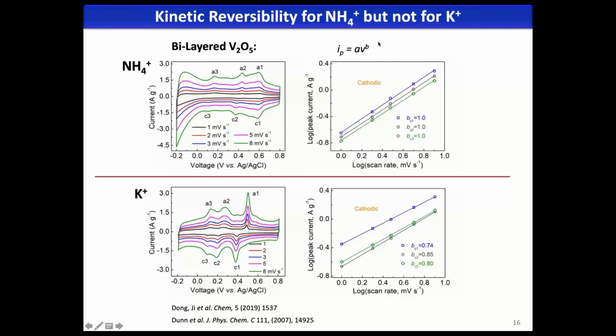And if you use this well-known equation, where v is the scan rate in a CV, and the B value: if the B value is 0.5, we call that diffusion controlled. Typically we say that's redox reactions, but now the definition needs to be better defined. If it's 1, it's non-diffusion controlled. In other words, the electrochemical behavior is faster than the time scale we gave in the instrument. So we call that capacitive. And for ammonium, it is just unity, just 1.